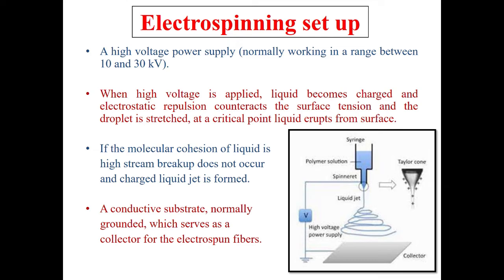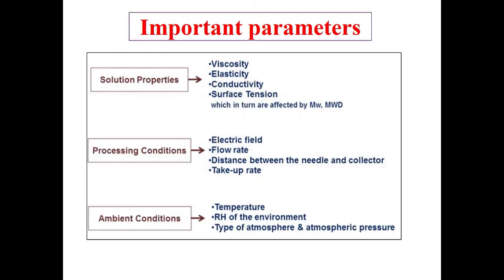At a critical point, liquid erupts from the surface. If the molecular cohesion of the liquid is high, then stream breakup does not occur, and a charged liquid jet is formed. A conductive substrate, normally grounded, will serve as a collector for the electrospun fiber. These are the important parameters associated with this particular setup.